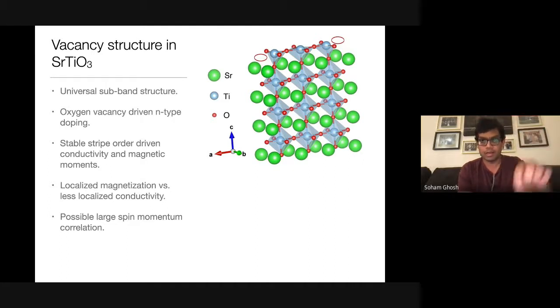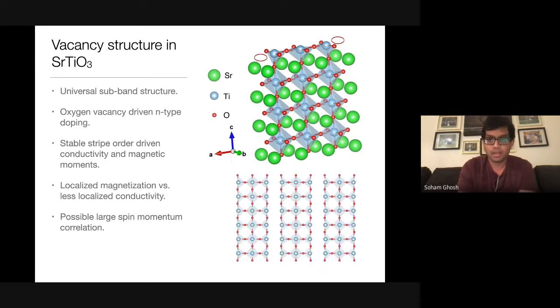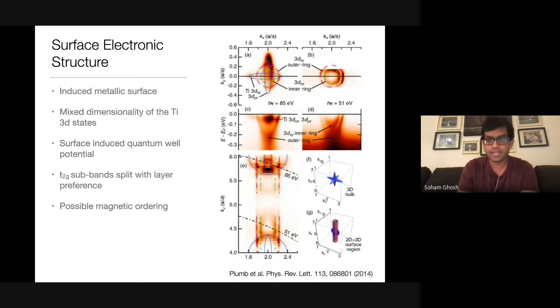So you have a line of oxygens missing on the surface, which is given in these red circles on top. And the result of that is that the electron gas, which leads to it being a metal, is delocalized. Those electrons can move around. But now you also create electrons which are localized and which give rise to magnetism. So essentially what you have are these stripes where one part of the electron states become metal and move around, and the other part of the electron states become localized and create magnetic moments.